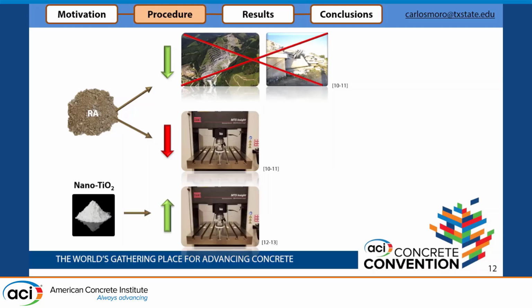So we were thinking that if we add nano titanium dioxide, a very small material, we saw that this alone increases the strength. So we asked, what happens if we use a small amount of nanomaterials? It could overcome the decrease in compressive strength that the recycled concrete aggregate has. For that, we did a life cycle assessment accounting for all the different impacts until the production stage, and also mentioning that we didn't use coarse aggregate, we used recycled fine aggregate, which normally is also a part of the recycled aggregate that is not considered either.